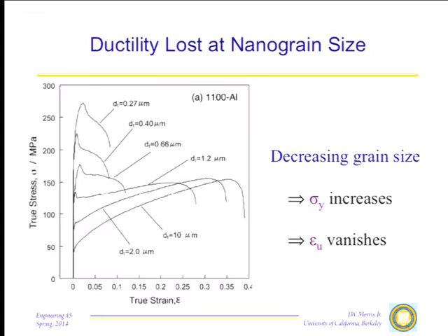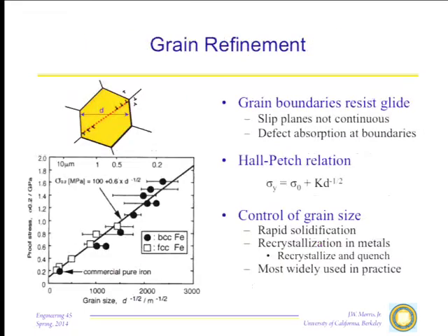And in particular, as I told you earlier, in the specification of structural materials, structural metals, it is very, very common for the customer, the user, to specify the strength ratio. Unless you can give them an ultimate strength which is sufficiently above the yield strength to give them a cushion, a safety factor in service, they don't want to use the material. So things that have stress-strain curves that look like this may look great from a strength point of view, but you're not going to find them in many structures because basically they're brittle materials. So we use the grain size to control strength, but we are generally shooting for an intermediate grain size, an intermediate strength level, to get the right combination between strength and ductility.